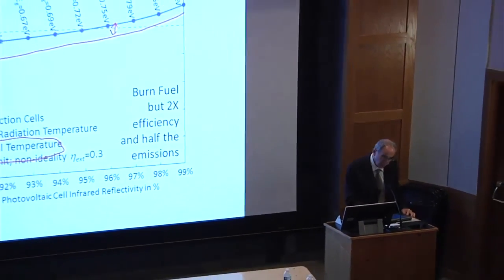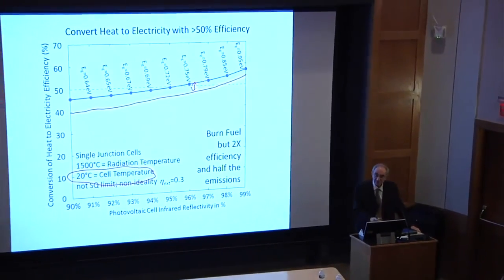Yeah. The curve that you used there, what temperature did you assume for that? That one was no ambient temperature for the 20 degrees cell temperature. Okay, so we've repeated these curves at 90 degrees cell temperature, and the curves go kind of like this. Okay, so you lose about 4 or 5% efficiency, but that's a very good point that you made.